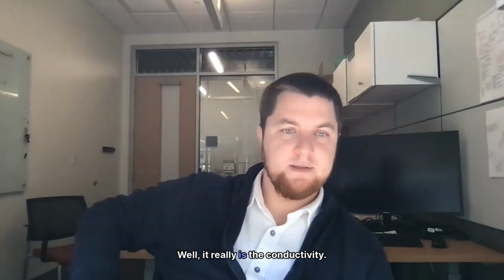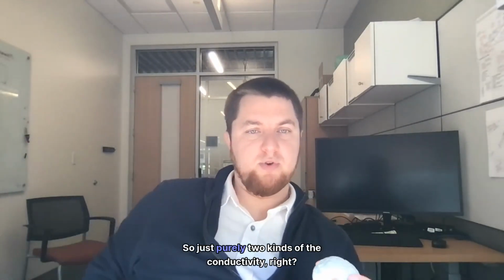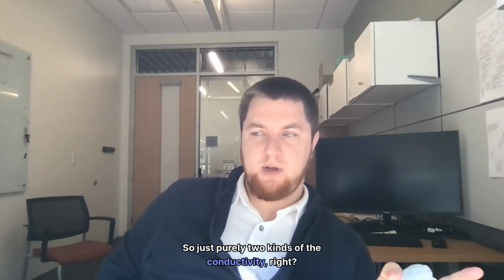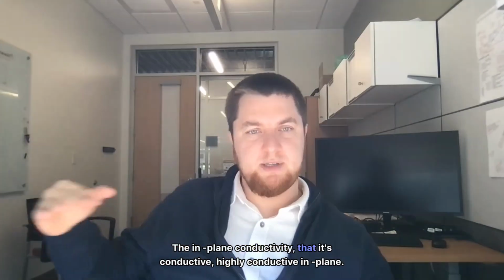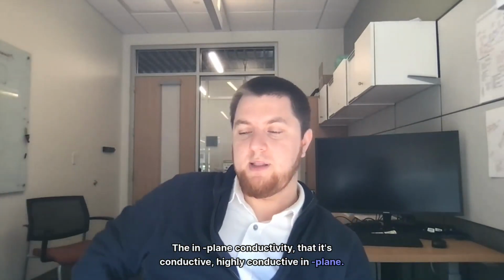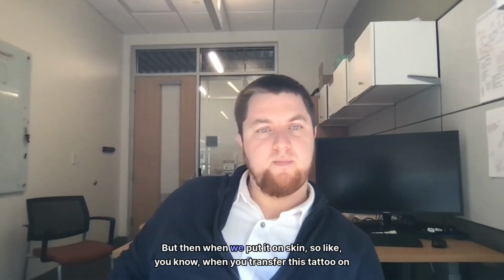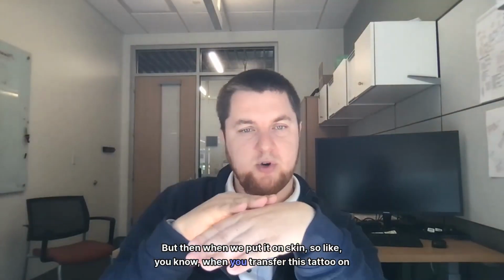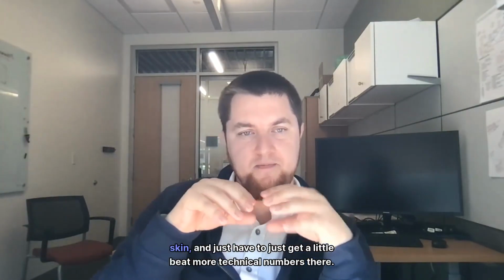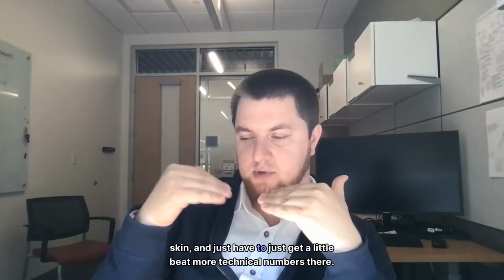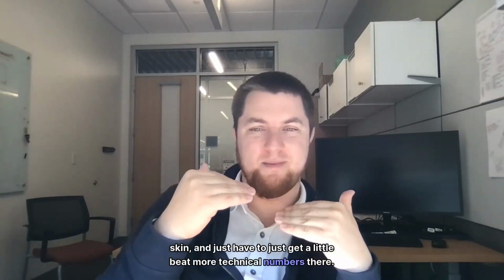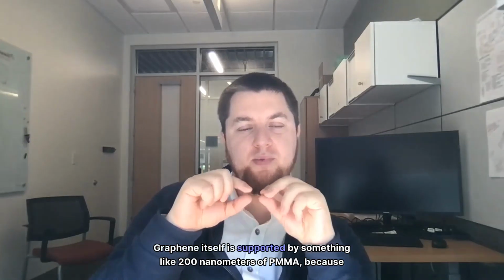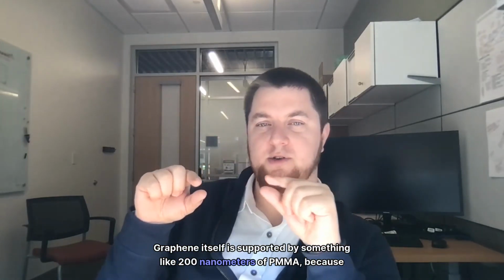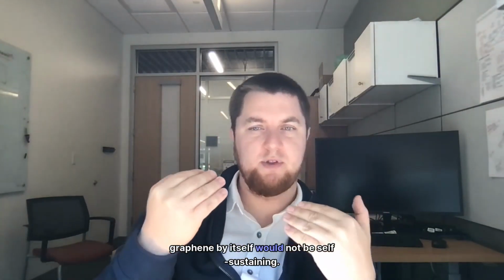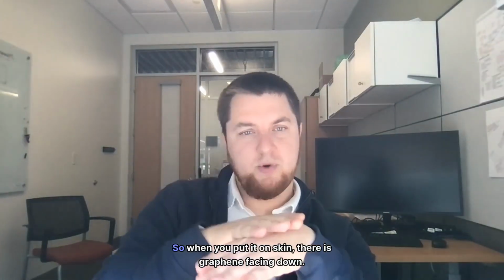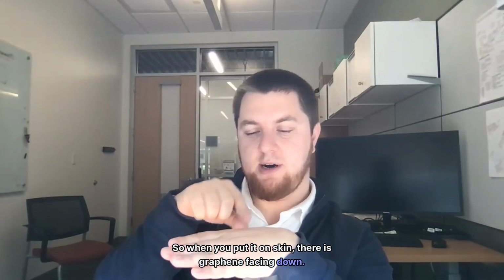Well, it really is the conductivity. So just purely the conductivity, right? The in-plane conductivity, that it's highly conductive in-plane. But then when we put it on skin, so when you transfer this tattoo on skin, just to get a little bit more technical numbers there, graphene itself is supported by something like 200 nanometers of PMMA, because graphene by itself would not be self-sustained. When you put it on skin, there is graphene facing down.